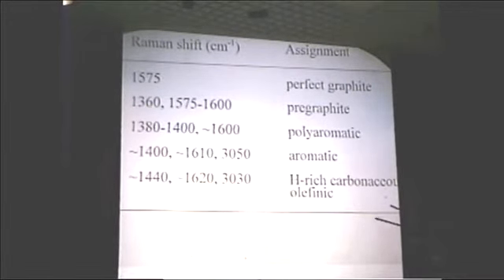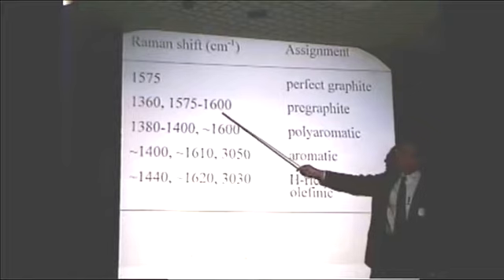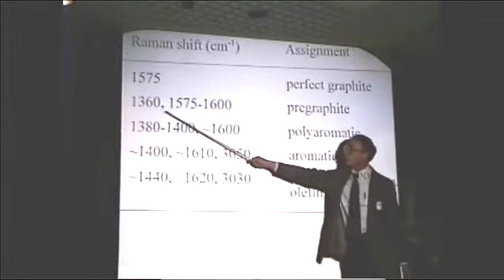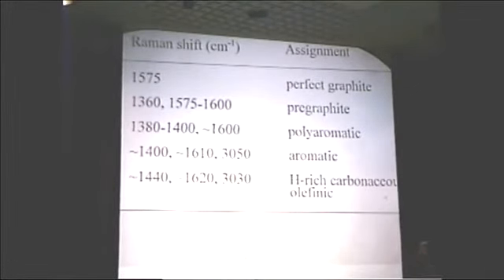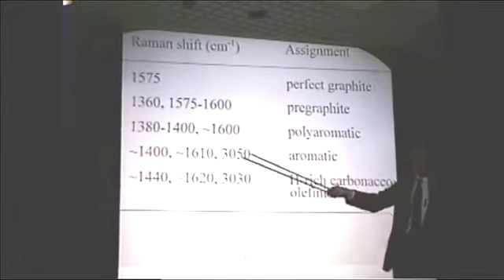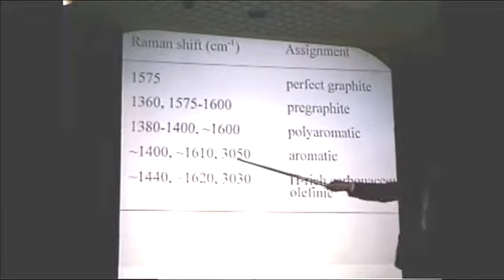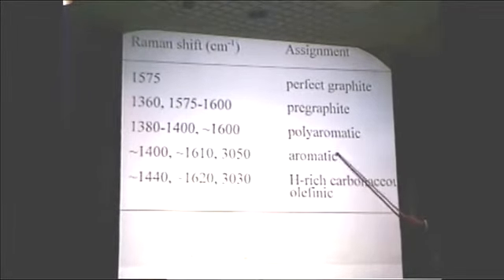So the perfect graphite gives us a single band at 1575. The sort of pre-graphite or microcrystalline graphite gives us bands down as low as 1575, and also this so-called defect band at 1360. The polyaromatic gives us a band around 1600 or maybe a little above. Aromatic up around 1610, so this would be mononuclear aromatic. And then the olefinic gives us bands at 1620 and above. So I think we have a nice way then of characterizing coke on catalysts.